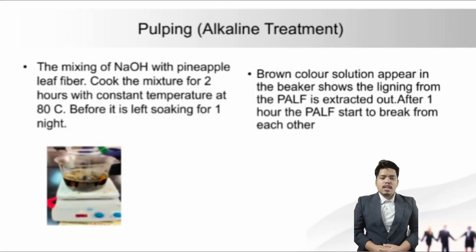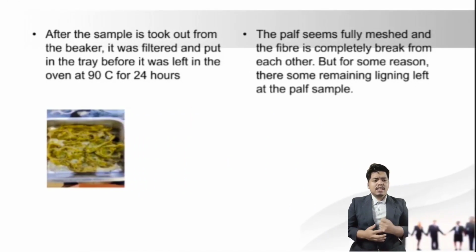Okay, so now let's move to the pulping method, also known as the alkaline treatment. Okay, so the mixing of the sodium hydroxide with pineapple leaf fiber. It will cook the mixture for 2 hours with constant temperature at 80 degrees before it is left soaking for 1 night. And then, after the sample is taken out from the beaker, it was filtered and put in the tray before it was left in the oven at 90 degrees Celsius for 24 hours.